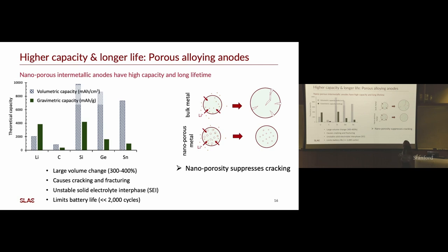So one of the solutions that we discussed with our collaborators from UCLA is developing nanoporosity in these particles. And the idea is that a bulk material will fracture as you lithiate it. The nanoporous material will just close up those pores. And so it allows you to have the volume change very locally to reduce the stress and allow those pores to close. And so you won't have this large volume change.